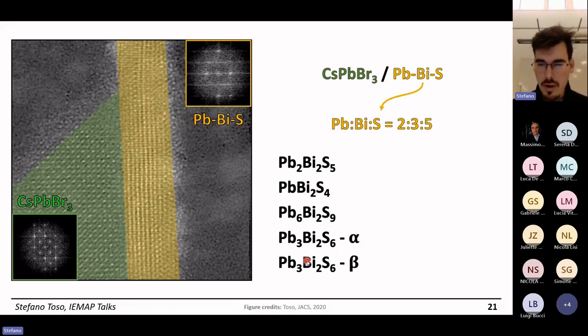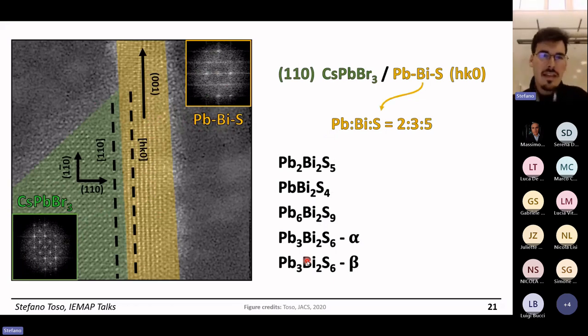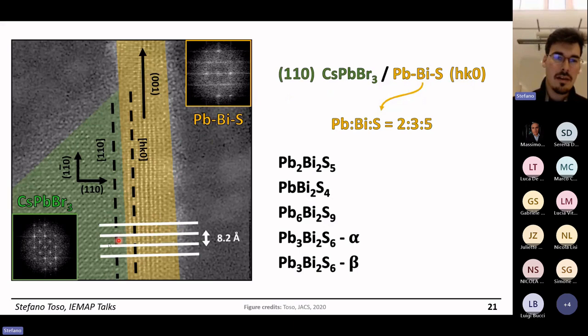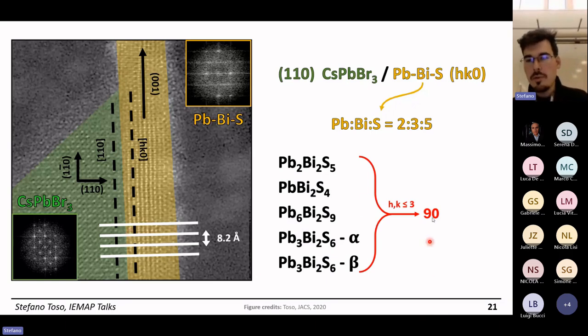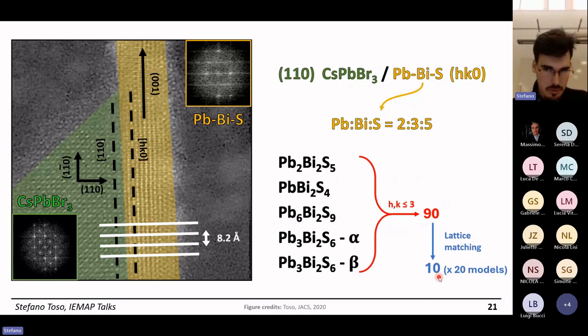So here is where we resorted to our tool. First, we extracted some crystallographic information. I'm not going too deep into it, but from the analysis of these FFTs, you can learn something about the crystallographic orientation. You know the plane that the perovskite is exposing, you know the plane that the bismuth lead sulfide is exposing. After that, you notice that you have another epitaxial relation here. Basically, the planes continue each other at the interface, which is also important to discriminate between the options, and you can feed this information into the model to lower the number of possibilities. If you have no idea whatsoever of which material this is, you end up with 90 possible interfaces given these Miller indices. Each of them comes with about a dozen models, so the complexity of the problem grows really quickly.